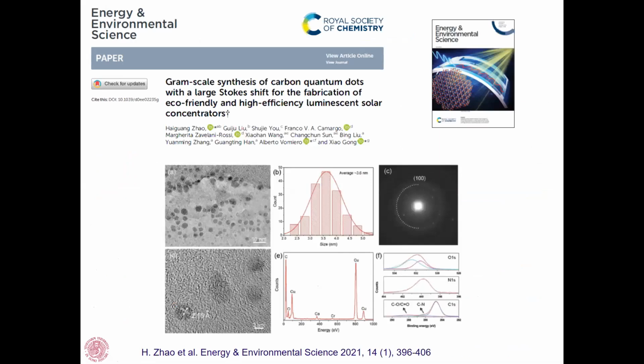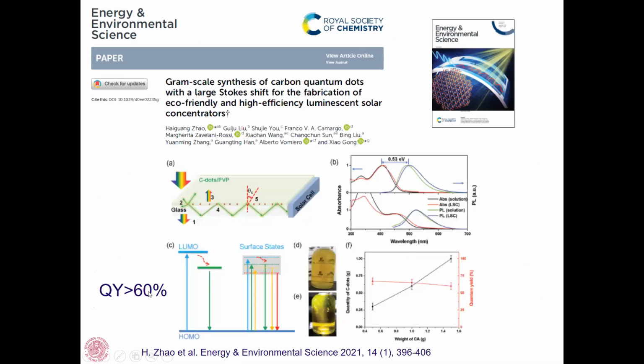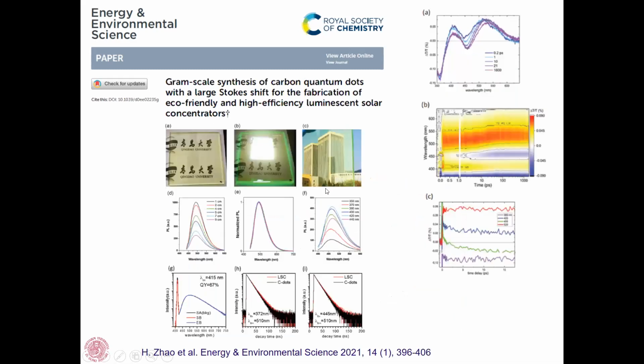And then the last one is about the possibility of using carbon dots with a new method developed by Professor Rogak using a vacuum system. There is the possibility to obtain carbon dots with quantum yield larger than 60%. We integrated them into luminescent solar concentrators, demonstrating that the Stokes shift is 0.53 electron volts, so it's pretty large, and we obtained a very high optical efficiency of the materials in a device.